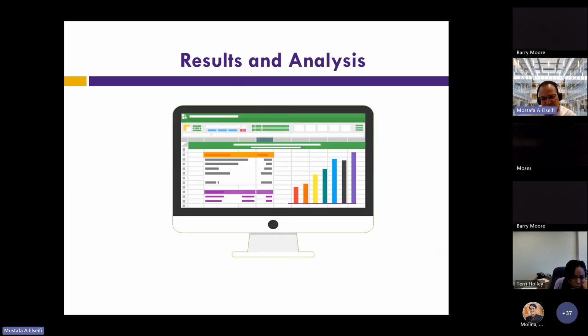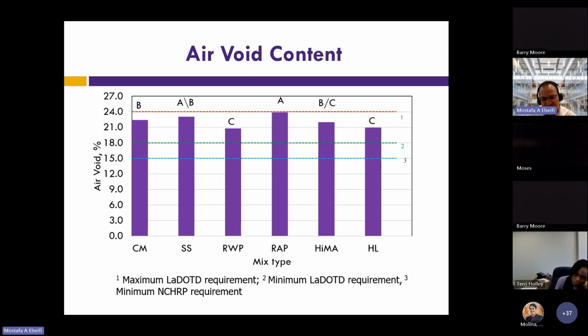All right, so showing you the results of our investigation. The air void of the different mixes, what I'm showing here, we have the 6 mixes, and we defined the abbreviations before. CM means control mix, SS means steel slag, RWP means recycled waste plastic, RAP is reclaimed asphalt pavement, HiMA is high polymer modified asphalt, and HL means hydrated lime. In terms of air void, we want to achieve between 18% and 24%. So anything in this range is acceptable from a specification point of view. The blue line is what is recommended by NCHRP 155. You can see that all our mixes satisfied this range,